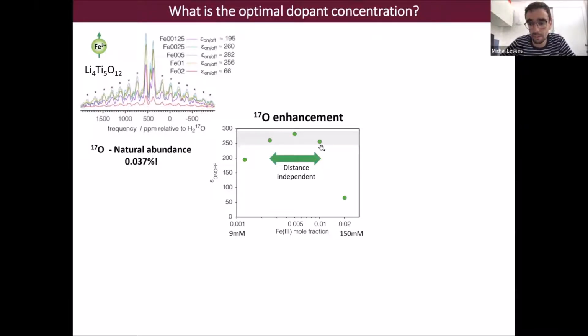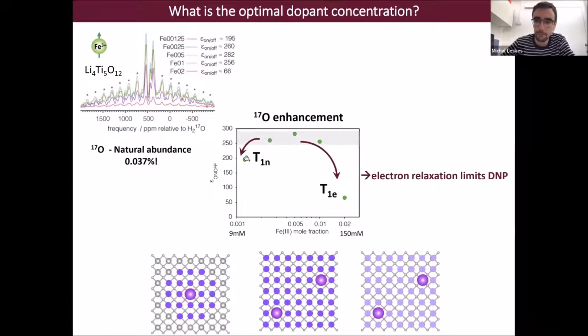Of course, when we increase the concentration, the build-up time will be shorter and shorter. However, this distance independency phase ends on both sides of this figure. The reason is that at low concentrations, at some point the intrinsic nuclear relaxation time starts kicking in. So very remote oxygen-17 nuclei from the paramagnetic center start relaxing due to their intrinsic nuclear relaxation mechanism, and therefore they cannot be enhanced as efficiently. On the high concentration side, the electron-electron interaction starts becoming stronger and stronger, and therefore the electron relaxation time drops, and the DNP enhancement will be less efficient.